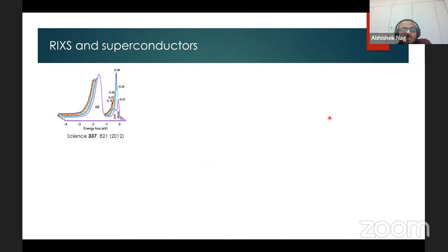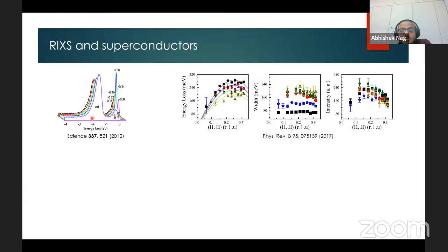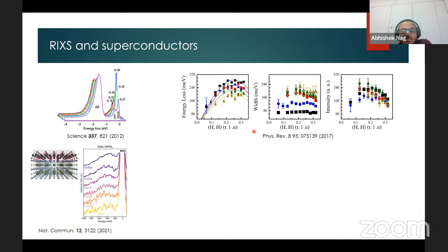One of the early important works found the presence of charge ordering in yttrium barium copper oxide, apart from orbital and magnetic excitations. And then RIXS was also used to study the doping dependence of magnetic excitations across the cuprate phase diagram, providing key insights. With the development of RIXS instrumentation, it is nowadays possible to study excitations in the extreme limits of modern day materials. For example, you can see here magnetic excitations in a monolayer, or basically a unit cell thick, of iron selenide using iron L-edge RIXS.